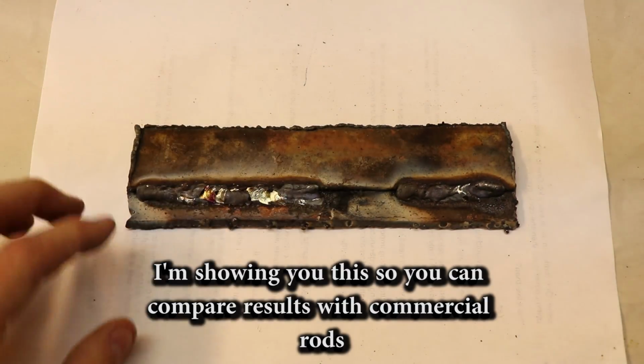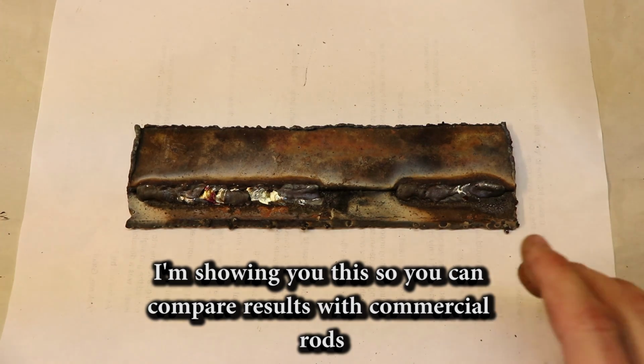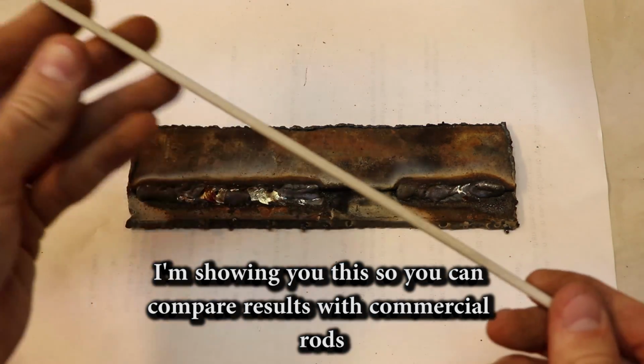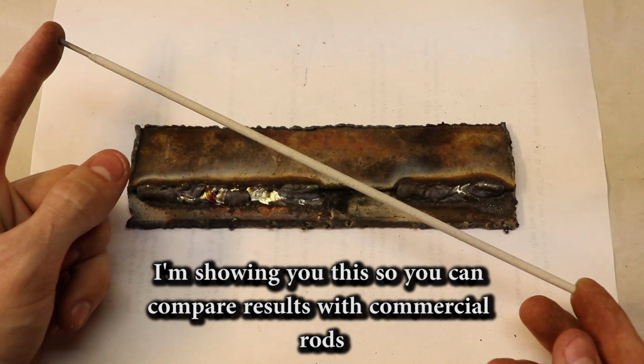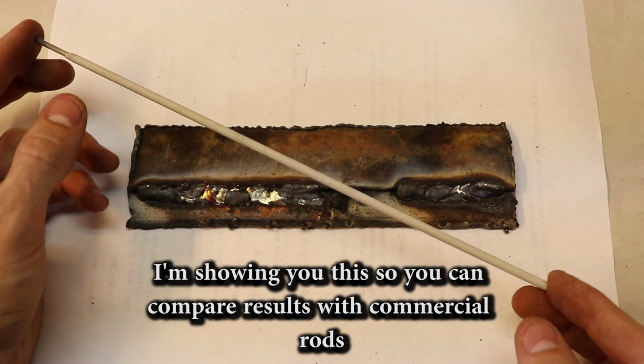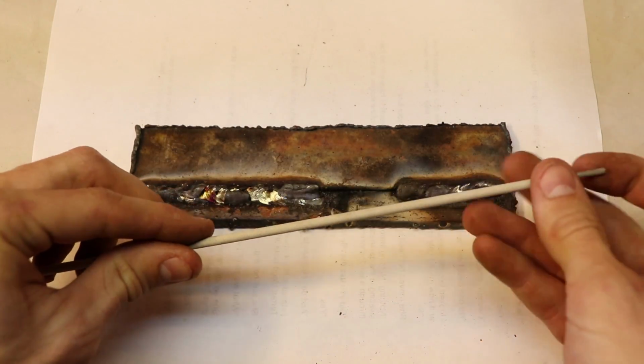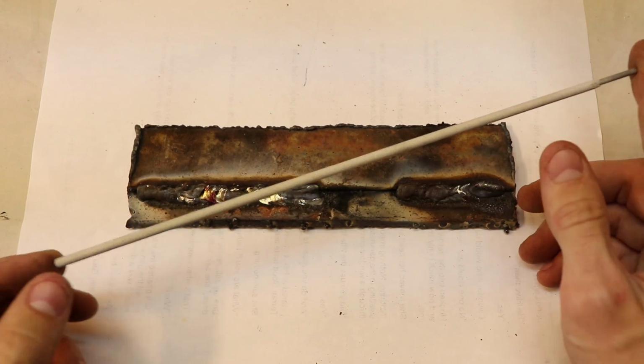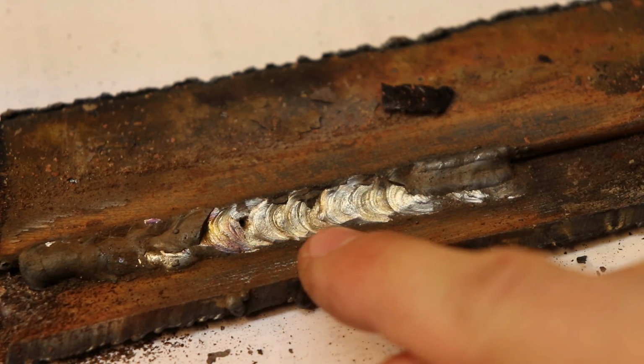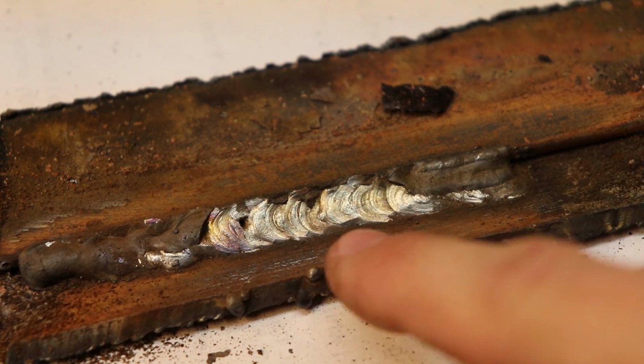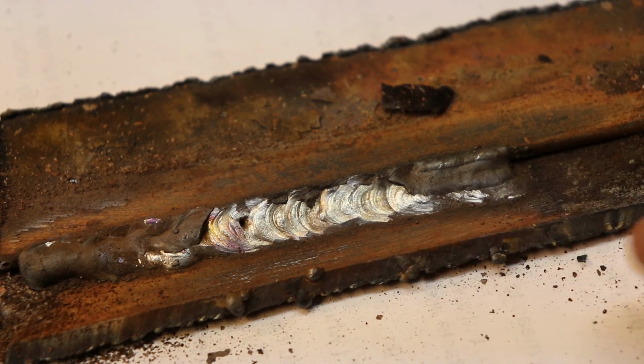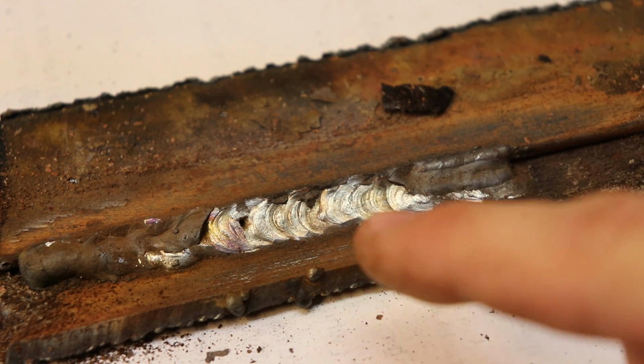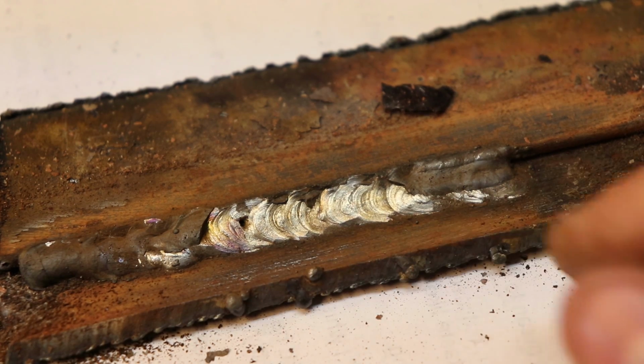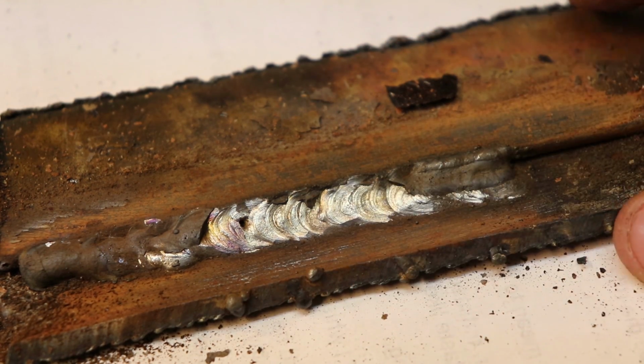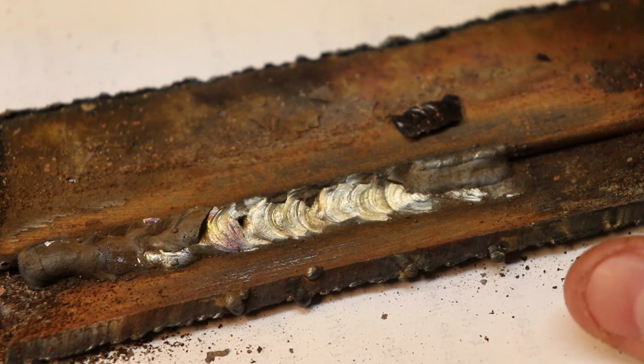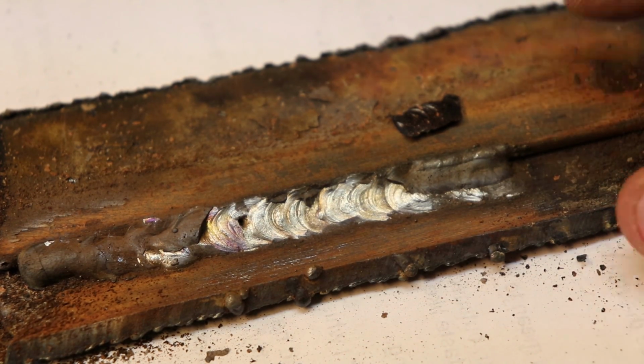Alright, so let's start off with my control. So this is my control. These welds were done by this rod. This is most likely a 6011 rod. I think this might be a calcium carbonate based rod. And you can see that the weld is consistent, it's uniform, it has sort of a nice pattern to it, which also indicates that I was going in a consistent manner along the weld, and it seems like it did join the two pieces of metal pretty well.